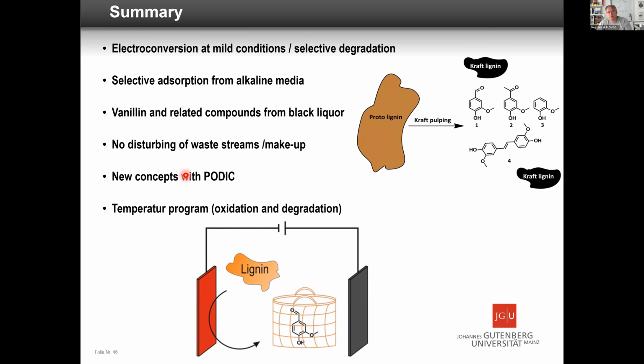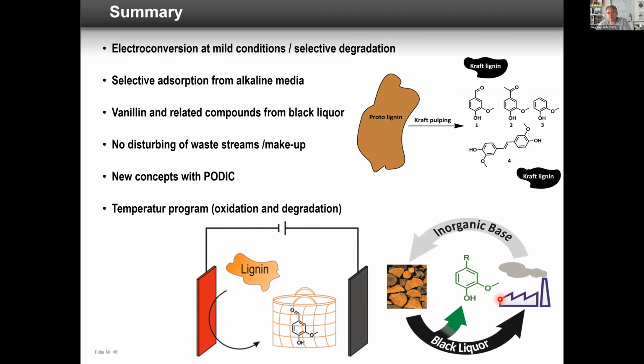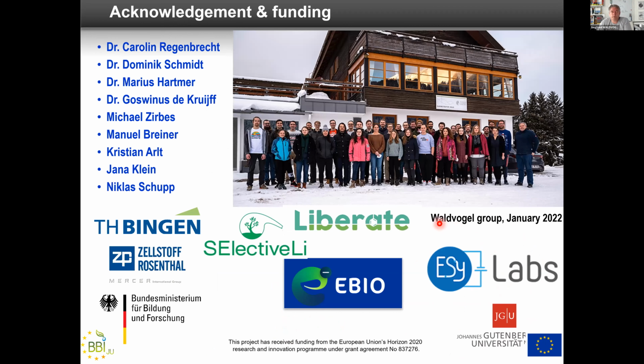We have new concepts using PODIC, peroxydicarbonate, and the temperature program is the key here. That means the oxidation at mild conditions is important. Then you have the polymer, which is oxidized, functionalized, and the liberation of the vanillin at higher temperature is something which happens afterwards. And this allows you to not over-oxidize the final product. And the good thing is you can take out the chemicals and not disturb the industrial concept of the pulping system.